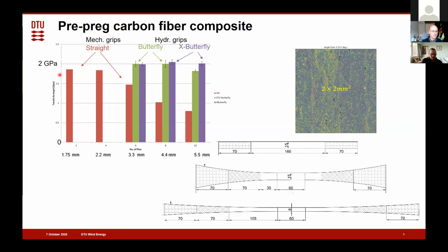This is mechanical grips for this case here. Then we can try to make other geometry. So this is this butterfly shaped sample we are using a lot also for fatigue test. If you do that, that's the green points here, and we can see that again we have a constant value, but if you come up to the thickest one, then you also get a decrease in that value.